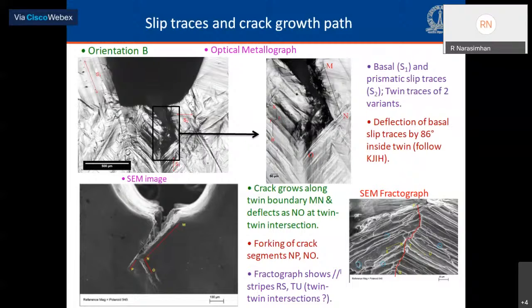Now, in all our experiments, the crack initiates before the peak load, and it grows stably along the twin boundary. And when it reaches the intersection between two twins, it gets deflected. You can see that in the right side image very clearly, top image, MN and NO are the two segments. The deflection has taken place at point N, at the intersection between two twins. We can make that out even more clearly on the bottom left side, which is a scanning electron microscope image, where you can see the deflection of the crack as two segments, MN and NO.